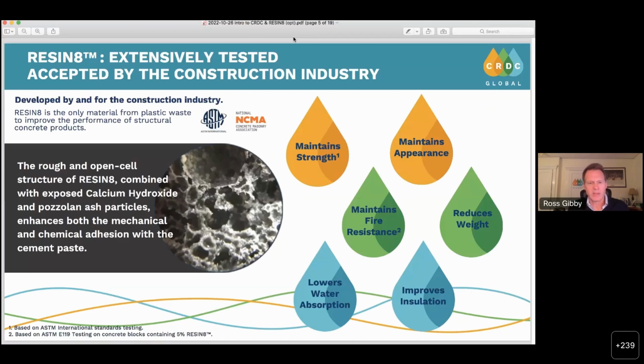So the cement paste permeates into all those little structures and completely encapsulates the particle. And when we also granulate it, we're exposing the calcium hydroxide, the lime, and the ash. And when we expose those particles, those are actually pre-existing in cement. Calcium hydroxide and pozzolans or ash are pre-existing in cement. So there's a chemical bond that happens there as well. So this is kind of the secret sauce on the concrete side, on the construction side, that allows us to maintain strength and provide that foundation for the construction industry. And as I mentioned, in certain concrete mix designs, we actually increase strength.